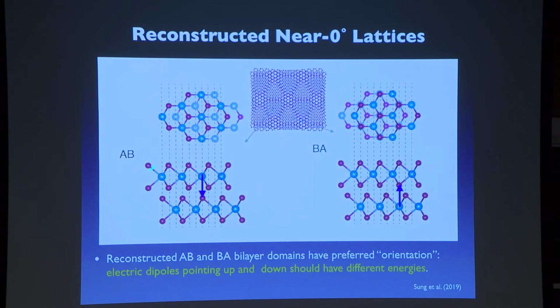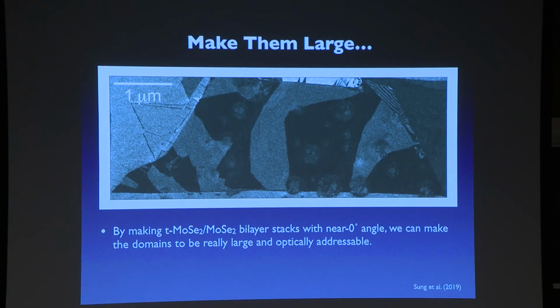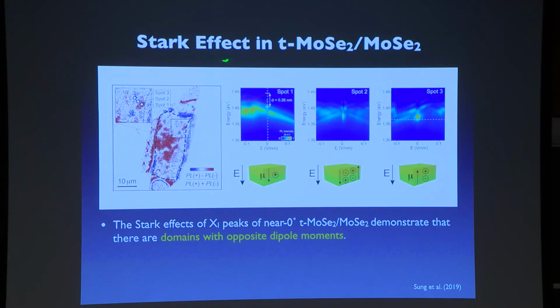So again, we can start to tell top and bottom, which means that when we generate interlayer excitons, then there should be a difference between interlayer excitons where the electron is sitting on top or the electron is sitting on the bottom, right? There should be a preferred dipole moment. And we can tell that by making these samples particularly disordered so that those domains are rather large, and then start to shine the laser light in different spots and measuring how they shift as a function of electric field. And you can see that depending on the region, one particular spot shifts in one particular direction, while the other spot shifts the other direction, which means that these are telling you exactly whether the dipole moment is aligned with the electric field or anti-aligned with the electric field.